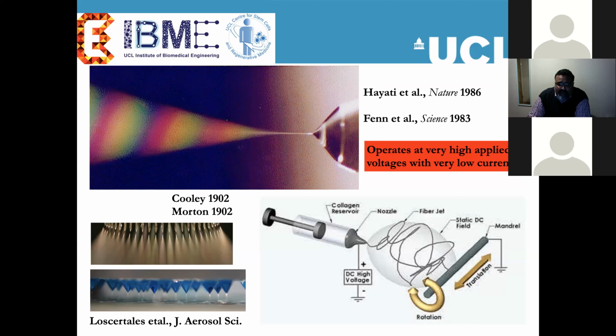Electrospinning is a sister technology to electrospraying, the only difference being the rheological properties. If you vary the liquid from something as low viscosity as water, not that high conductivity, or let's say ethanol, and you move to something like glycerol, you will be able to pull out a continuous filament. That filament on collection forms a random scaffold, and that is what electrospinning is.